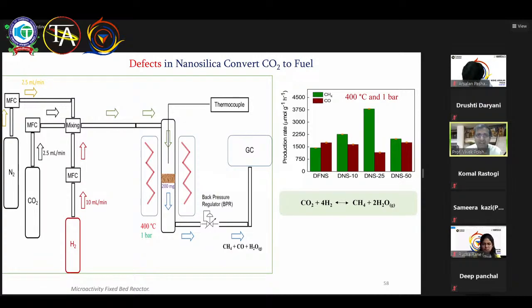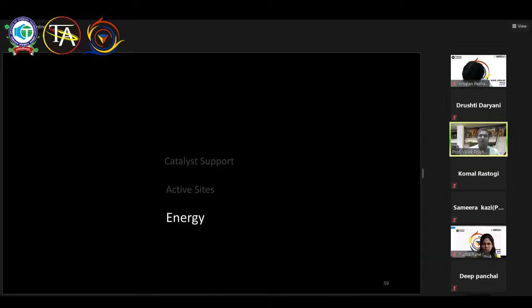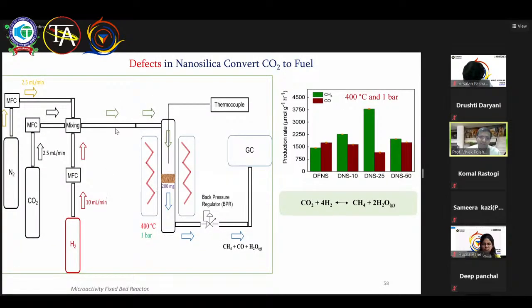Maybe I skip the technical details. The only drawback of this particular process, this is the typical reactor that we use. We mix CO2 plus hydrogen and pass it through the catalytic reactor, which is heated at 400 degrees Celsius, and the products were monitored by gas chromatography. The only drawback here is that I need 400 degrees Celsius. So this is an energetically heavy process. So now either I do the reaction at a lower temperature, which was not possible, or I get that 400 degrees Celsius from the sunlight.